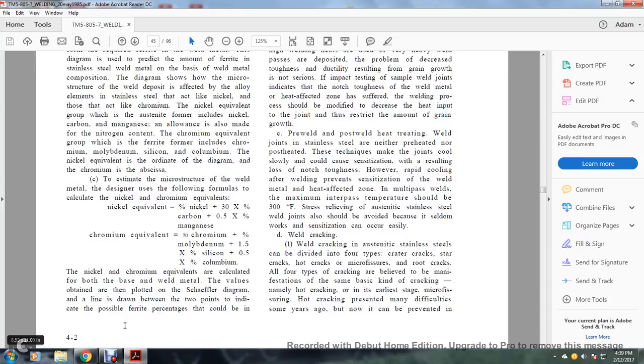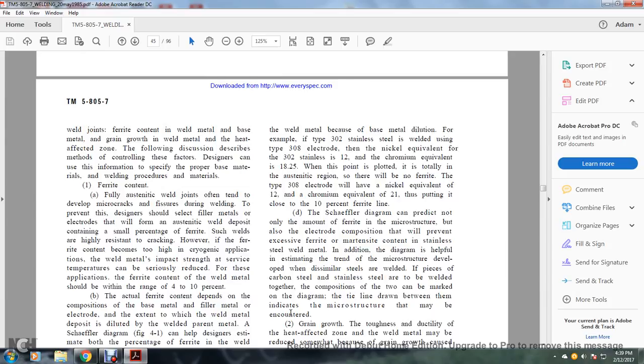To estimate the microstructure of the weld metal, the designer uses the following formulas to calculate the nickel and chromium equivalents. Nickel equivalent is equal to the percent of nickel plus 30 times the percentage of carbon plus 0.5 times the percentage of manganese. Chromium equivalent is equal to the percent of chromium plus the percentage of molybdenum plus 1.5 times the percentage of silicon plus 0.5 times the percentage of columbium. Nickel and chromium equivalents are calculated for both the base and the weld material. The values obtained are plotted on the Schaeffler diagram. The line drawn between the two points indicates the possible ferrite percentage that could be in the weld because of base metal dilution.